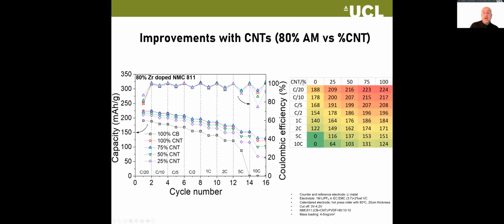And what we're doing is replacing that 10 weight percent of carbon black with up to 100% replacement of that 10% with carbon nanotubes. And what you essentially find is what you might expect, that as you add more carbon nanotubes, it seems to improve the performance, or you reach a limit. So at about 75% carbon nanotube replacing, so you've got 25% of carbon black as a percentage of the 80-10-10, it's that 10% that your 75% is of. You find you're reaching the optimum, and if you add more, it actually doesn't make it any better, or maybe even makes it slightly worse.